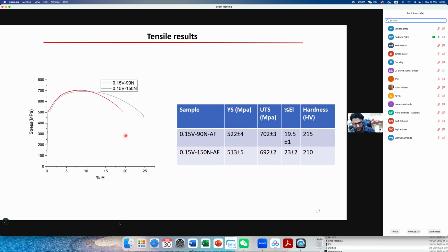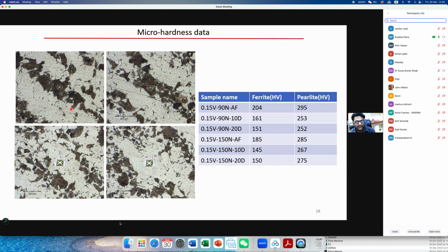So we were expecting that with increasing nitrogen concentration, the yield strength would increase significantly, but somehow in case of this as-forged steel, we are not getting that. So we have also studied the microhardness from both ferrite and pearlite regions. Here also, in case of 90 nitrogen as-forged condition, we are getting 200 hardness in ferrite and 295 in pearlite, whereas in case of 150 nitrogen, we are getting lower values in both ferrite and pearlite. And in normalizing, it is expected that the hardness will decrease in both ferrite and pearlite regions.